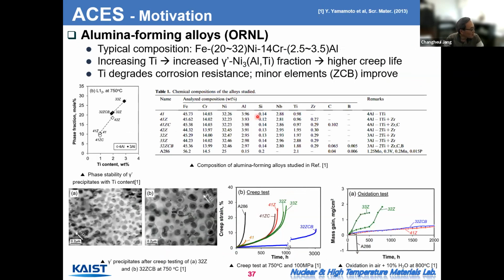And for that purpose, an aluminum forming alloy has been developed by the Oak Ridge National Lab in the United States that has roughly 20 to 30% nickel, and they added roughly 3% aluminum. Because of those alloying elements, they have the Laves phase and also NiAl B2 phase formation at high temperature. So that contributes to the creep resistance. But still, because of the low amount of aluminum and the relatively low amount of chromium, their corrosion resistance is not as good as other high temperature materials.